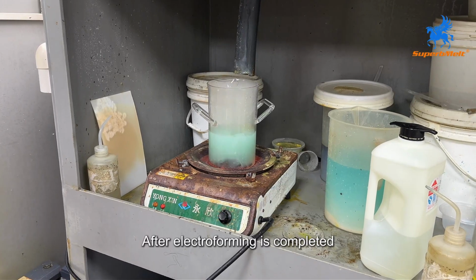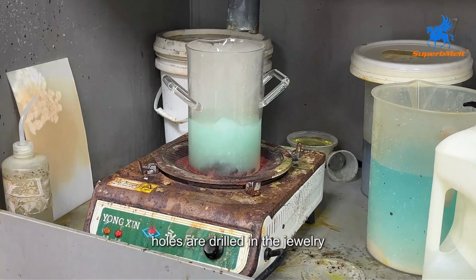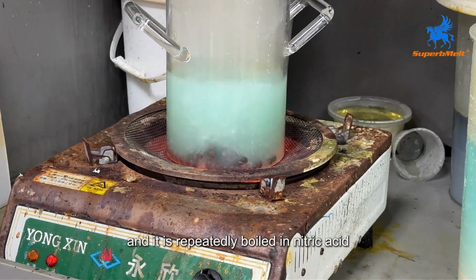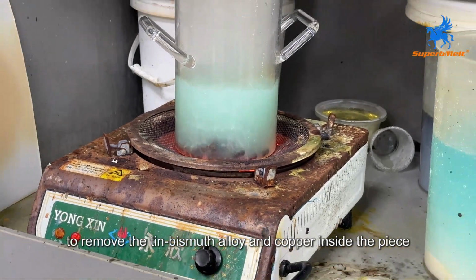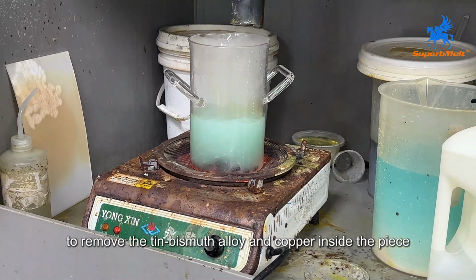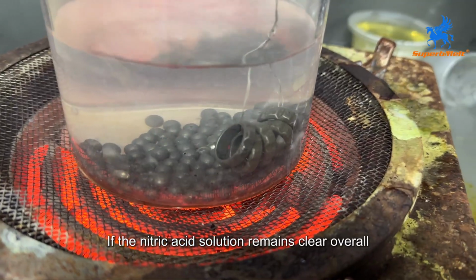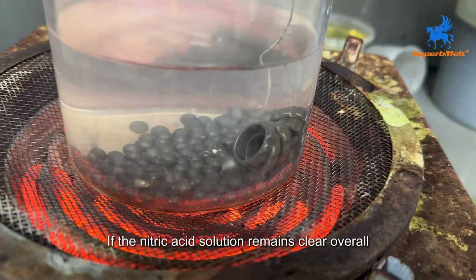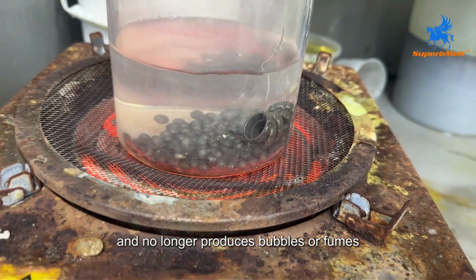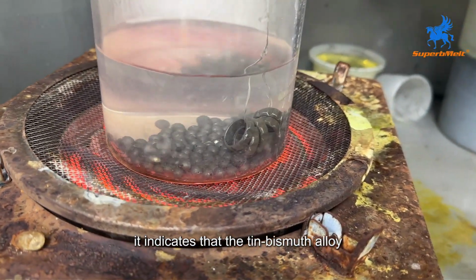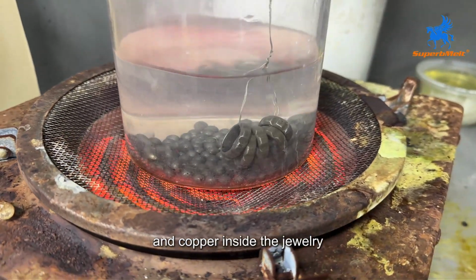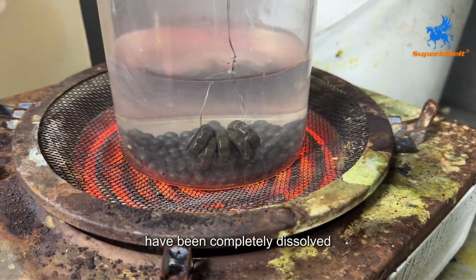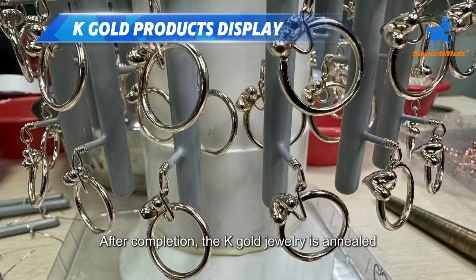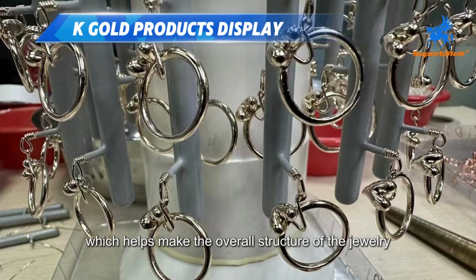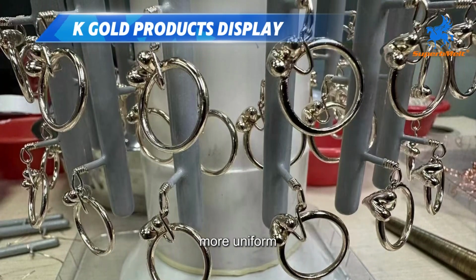After electroforming is completed, holes are drilled in the jewelry, and it is repeatedly boiled in nitric acid to remove the tin, bismuth alloy and copper inside the piece. If the nitric acid solution remains clear overall and no longer produces bubbles or fumes, it indicates that the tin, bismuth alloy and copper inside the jewelry have been completely dissolved. After completion, the K-Gold jewelry is annealed, which helps make the overall structure of the jewelry more uniform.